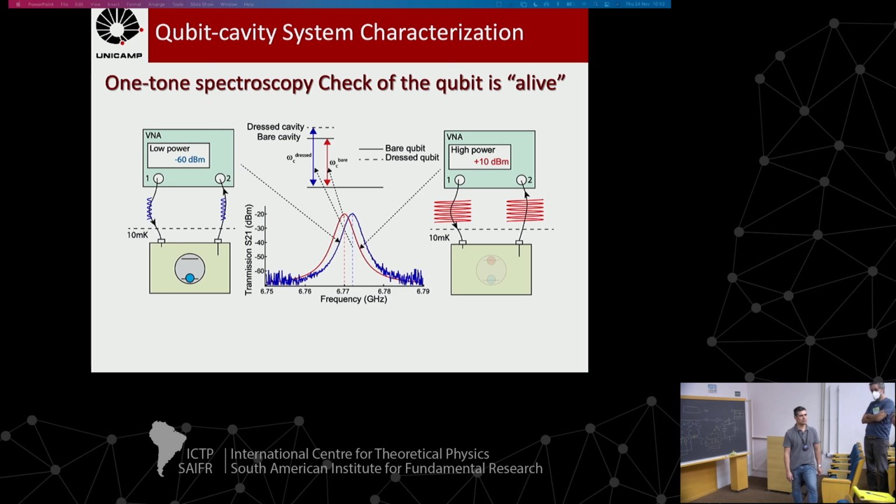Oh, yeah, so I have another question. I would also like to have an idea of the lifetime, because when you're building the chip, you can use it for some time and then you have to change it. When I say, okay, let's start to make a sample, I need to get the sample, and within 200 hours I need to have the sample inside of the fridge. If the sample is in the air more than 200 hours, I have to throw away the sample. Okay.